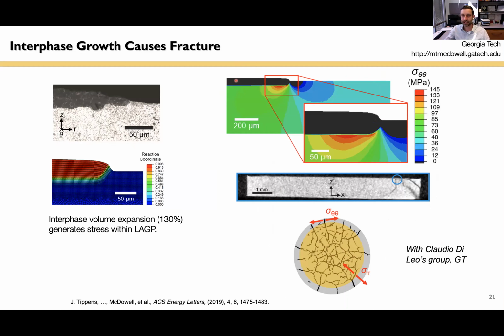There's lots of volume change. And so this volume change induces tension in the rest of the pellet. And this tension pulls the pellet apart. And this particular pattern is consistent with what we expect the stresses to be in the pellet. So this is a little bit different than maybe others in the audience may know of filament-induced fracture due to short circuiting in filaments. This is different than that because we have such an unstable solid electrolyte, but pretty interesting. In the long run, interphase formation is bad after all, but we're able to quantify how it affects failure here.